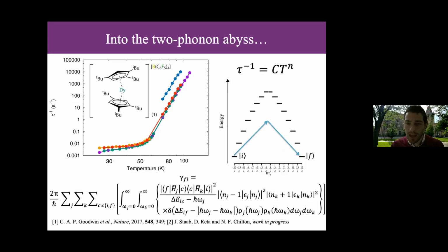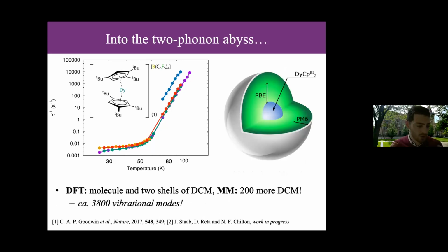Okay, so calculating this is a heck of a lot harder. And of course, you need an environment, because we are now talking about very, very low temperatures, which means low energies, which means low energy vibrational modes. And so the gas phase has these discrete high energy vibrations, and that's more or less irrelevant. And we can therefore calculate Orbach fine with that, but we cannot get the Raman. Okay, so we need an environment, and we can do this in the crystal structure. We're working on it now. That's a really hard problem.